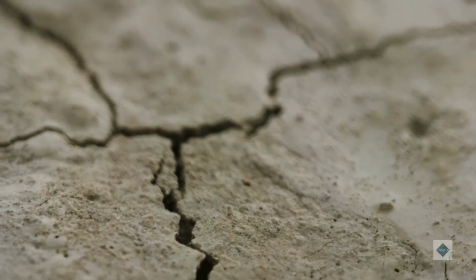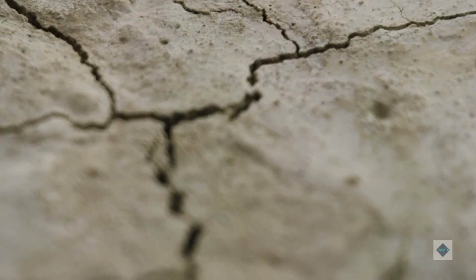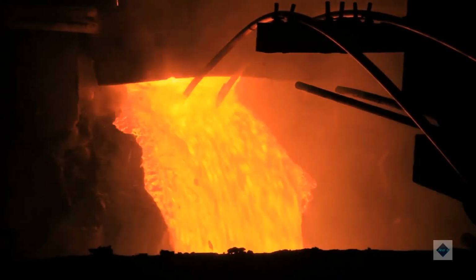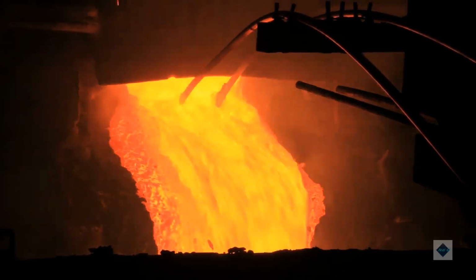These cracks are very difficult to prevent in the structures we are trying to build, so we developed a new strategy that allows us to self-assemble the particles while keeping the template wet. This prevents the films from cracking, but because the particles are wet, we have to lock them in place using electrostatic forces so that we can fill them with metal.